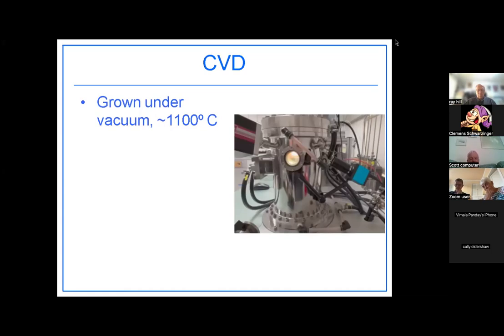So if you're using a hot filament, you're looking at 10 to 100 microns per hour, but it's less pure. Using the microwave, it's slower, but you can get flawless material. And the carbon is deposited on the cooler surface. And after 3 days growth, this is what you look at when you pull it out of the reaction chamber. So the picture on the right is 3 days worth of growing.